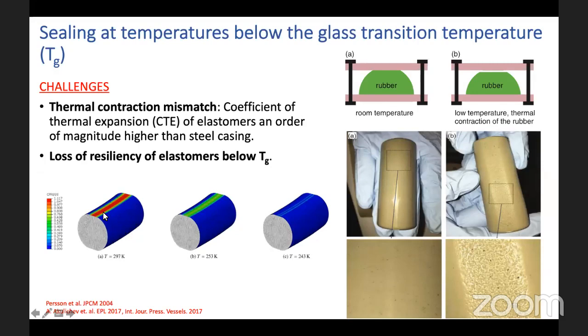So here, if you see the contact pressures that were calculated by simulations by Akulichev, he showed that as you decrease temperature, the contact pressure decreases. This means that if you want to seal some fluid and the temperature decreases, the contact pressure is low. So the fluid pressure will overcome this contact pressure, and the fluid will start leaking. And at low temperature, what happens is, for example, you see the figure here.